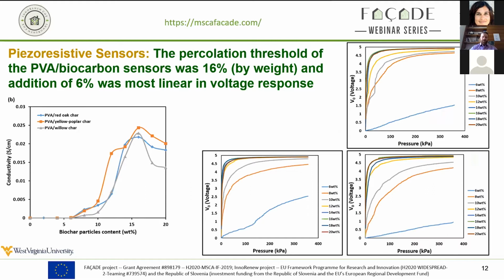Here are some results on how that works as a pressure sensor by adding different percentages, anywhere from 6% up to 20% by weight. If you're looking at a long range of pressure, so 0 to 350 kilopascals of applying pressure to this sensor, adding 6% by weight is the best. It's more linear and it covers the entire range. And if you look at any of these graphs on the right, you can see once you get to a certain pressure, they just flatten out. So that means that sensor wouldn't be able to tell the difference between 200 kilopascals and 300 kilopascals of pressure on that sensor.